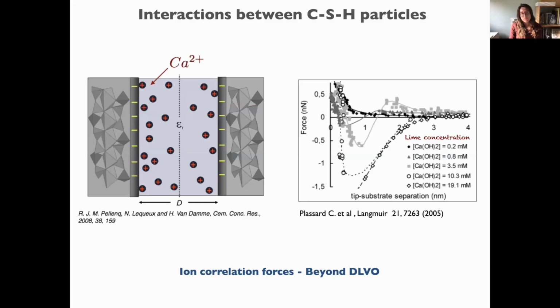So if we go back to theory, we know that DLVO can predict what's happening in these cases, and usually it will predict repulsion. But DLVO is a mean field approach, so it has limitations, and its validity stops if we have high surface charges or divalent or trivalent ions, which is the case here for cement.